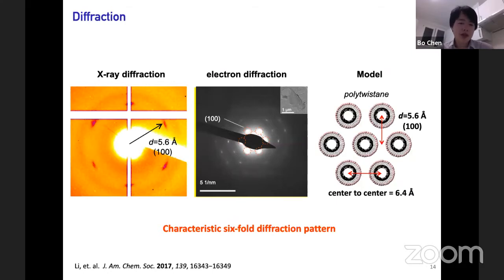Some diffraction characterizations showing you the order. The first one is very important, the diffraction. The sample shows this very unique six-fold, single-crystal-like six-fold diffraction spots or patterns, not only from X-ray, but also from electron diffraction. And this unique pattern can only match the simulated diffraction pattern for a packed nanothread crystal. Here we are using a polytwistane as a nanothread model, but if we put in another type of thread, that's okay, you will get similar d-spacings.